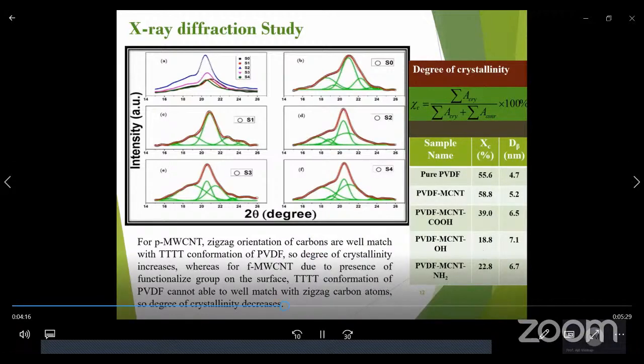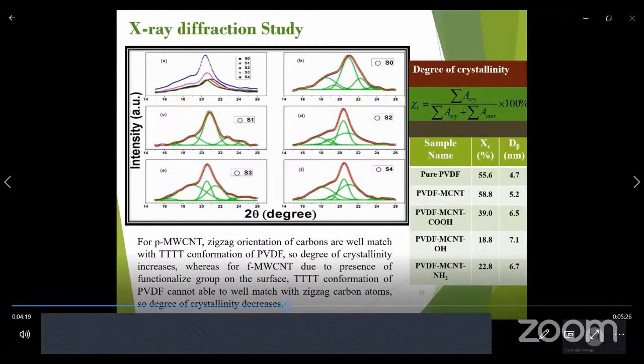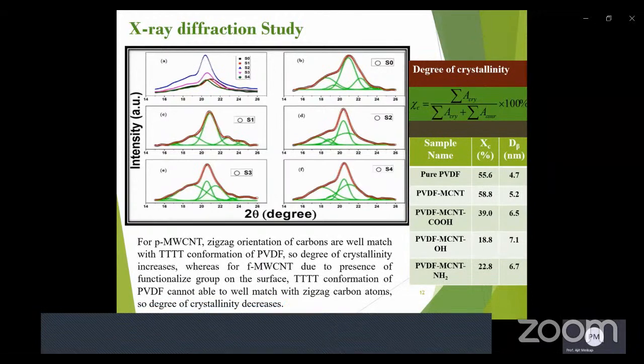non-functionalized MWCNT. The XRD analysis suggests that the degree of crystallinity reduces for functionalized MWCNT PVDF than pure MWCNT PVDF, because for functionalized MWCNT, due to the presence of functional group on the surface, the TTTT conformation of PVDF cannot well match with the zigzag carbon atom, so the degree of crystallinity decreases.